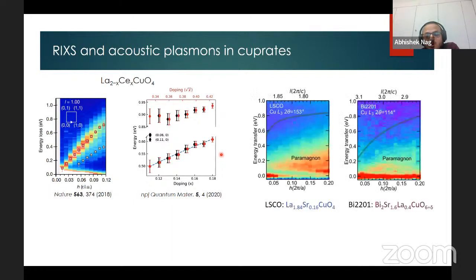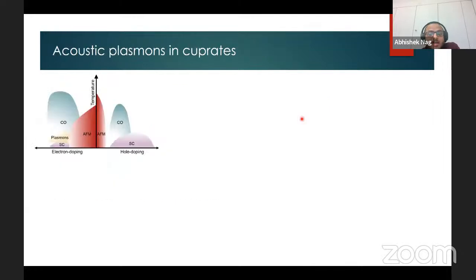Surprisingly, in the hole-doped cuprates, which were much more widely studied using copper L-edge RIXS, there was no indication of such acoustic plasmons. So the character of the low energy charge fluctuations becomes questionable across the phase diagram. Why should the hole-doped cuprates, having a similar layered structure, not have such low energy charge fluctuations?